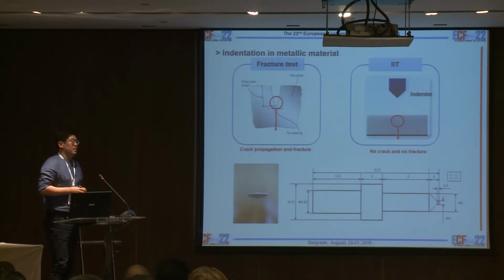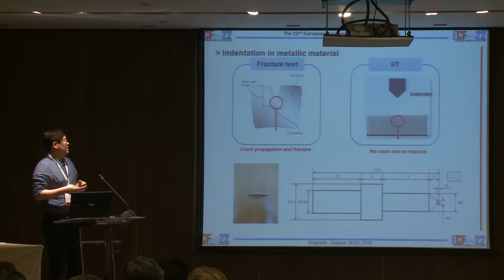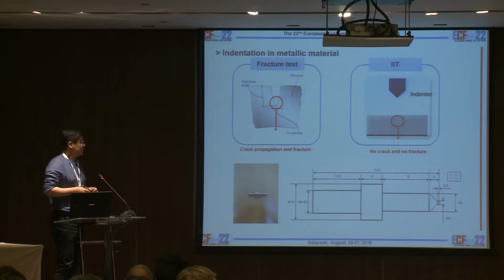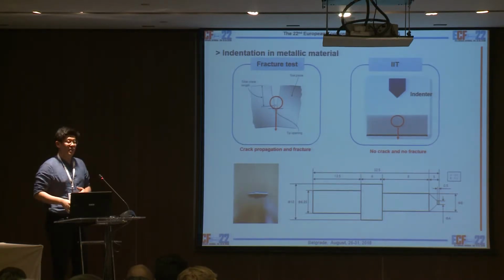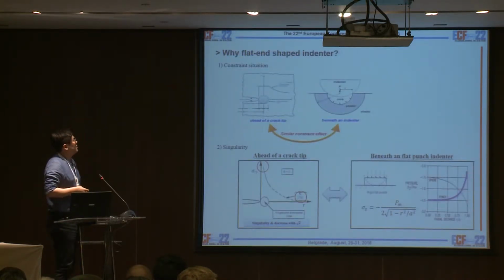So we tried testing it several times with a variety of types of indenters. We tried to find the similar points between the fracture toughness test and the instrumented indentation test. And finally, we decided on the flat end shaped indenter with a 100 micrometer diameter. So why did we choose the flat end shaped indenter?